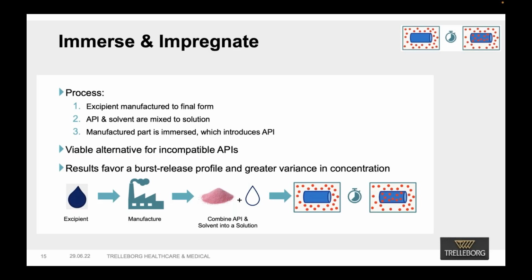There's a swelling that occurs with that sample, and that allows the pharmaceutical to basically, we'll refer to it as, impregnate that unit. So once you remove that solvent from the system, you're left with a finished component that is both device and drug. So again, the advantage of this is that we're introducing the heat for the manufacturing process, and we're completing the curing process prior to the introduction of the pharmaceutical. And that's really where there is some place for this process within formulation here.